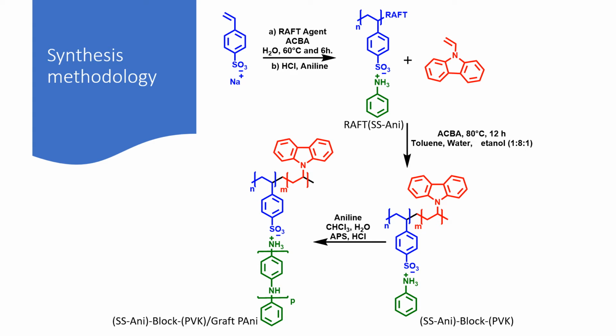polyanilinium styrene sulfonate. In a second step, we elaborate a block copolymer using carbazole in a heterogeneous polymerization using water, toluene, and ethanol as a co-solvent. Finally, using the block copolymer and employing interfacial oxidative polymerization, we graft the polyaniline chain to create the terpolymer system.